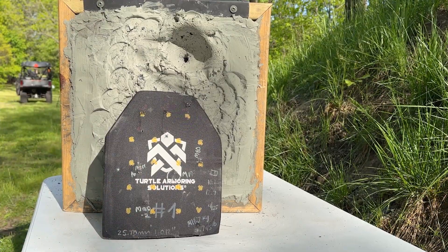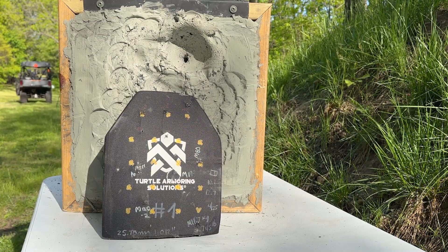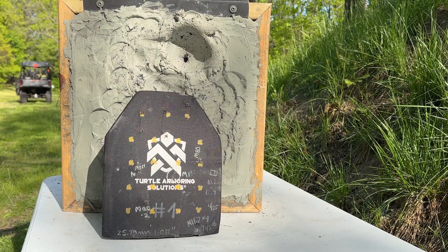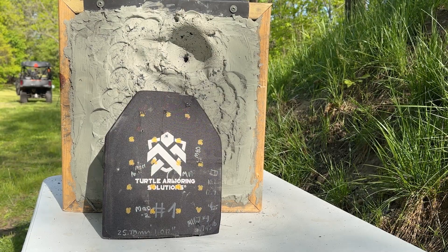The mild steel core did not penetrate through the entire thickness of our polyethylene — it actually pushed up and out. But our M80 ball was stopped. And the backface on that is a lot less than plate number two — I would say that sample material number one is a far superior material, with 29 millimeters backface. This particular plate was even lighter than sample number two. I think at this point we've satisfied his workflow and shown that this sample is very, very capable. I hope he will accompany this with lab testing showing that this will stop M855 from the 3115 feet per second lab spec. Very, very good job.